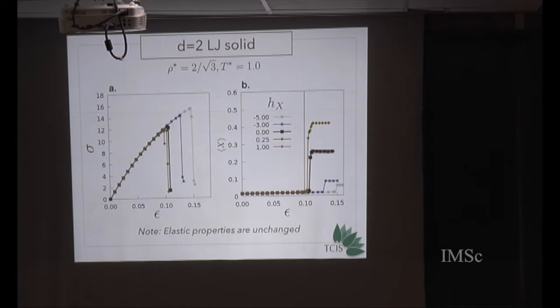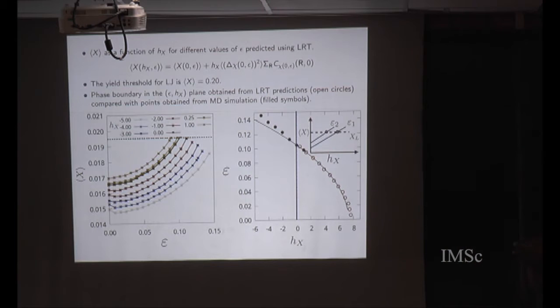Okay, so there is this jump in this collective coordinate. I am not calling it an order parameter for a very valid reason. And elastic properties are unchanged. If you were to look closely in this region, you would see that again the value of this quantity at the jump seems to be constant over some values of h. Okay? So it's sort of roughly constant. Now this gives us an idea.